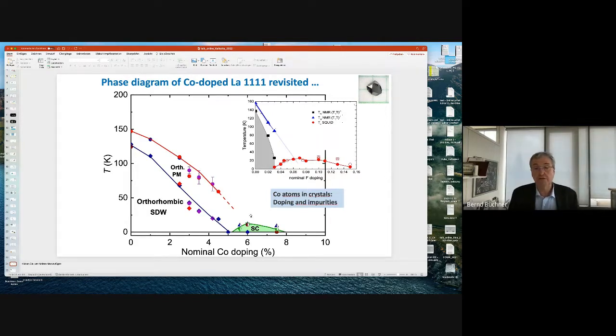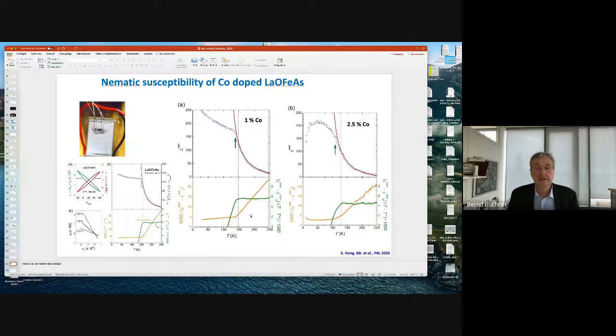So let's have a closer look at these nematic transitions, at this nematic instability. What I now present to you are measurements of the resistivity under strain. This is a typical experiment: you apply a strain and you measure the resistivity. Then you go back and forth, and you plot the change of the resistivity as a function of the strain. You get these slopes, and from these slopes you derive the nematic susceptibility. So the derivative dη versus dε gives you this nematic susceptibility,